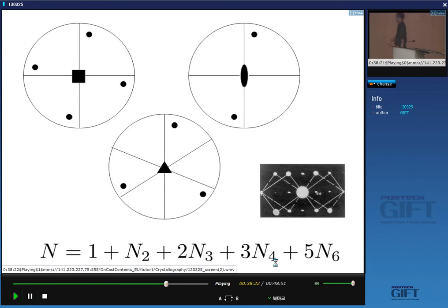So how many triads do we have in a cubic system? We have 4 body diagonals, right? So that's 4 times 2 is 8. We have 3 cube faces, tetrads. So 3 times 3 is 9. 9 and 8 is 17. Okay. 17, then we have this one here, which makes it 18. And then we have 6 dyads. So 6 and 18 is 24. So there are 24 symmetry-related operations in the cube.